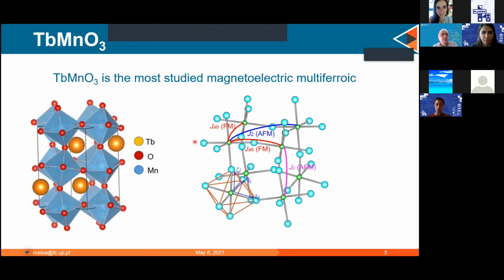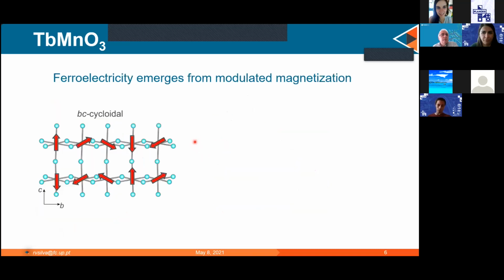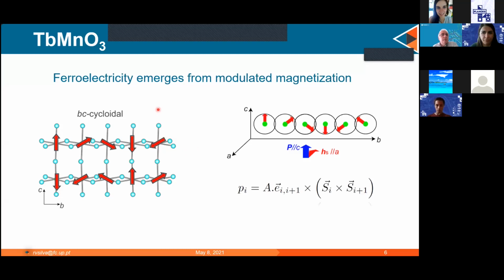And so because the material doesn't know how it wants to order, it makes different kinds of ordering that, such as this one, is modulated in space. So you have the spins in one octahedra of the manganese ordered in one direction, and then they rotate from octahedra to octahedra, and they are modulated in space. The good thing about this is that in the case of this cycloidal order, this modulation breaks the center of symmetry, which means that you have a ferroelectricity coming from the magnetism, as it's shown here.